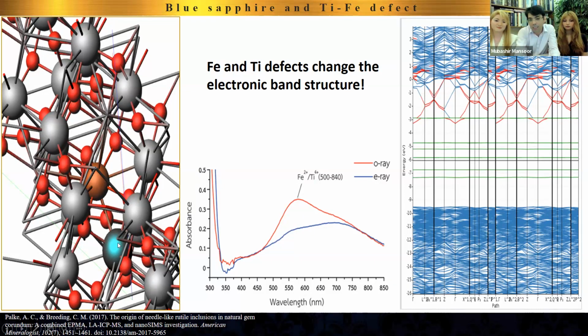If we have an iron and a titanium sitting side by side in places of the aluminum atoms, then we would have these beautiful changes in the band structure. So remember, last time when we saw this band structure, in between there were no lines. It was completely empty. And we said the incoming light would require 9 electron volts. And since the sunlight does not have that kind of energy, there would be no optical transitions. Electron would not be able to jump. And that means the gemstone would be transparent and colorless.